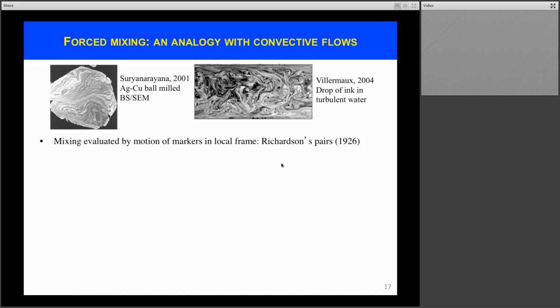What we realized is that a key point in understanding the origin of this length scale selection was to look at the mixing that's forced by plastic deformation. And here it's interesting to make an analogy with convective flows. On the left-hand side is a cross-section of a particle of copper silver that is being ball milled, but stopping before one has formed a solid solution or nanocomposite. And you see these stretched fibers or platelets of copper and silver. This is somewhat reminiscent of how materials would flow in a liquid. There's no deeper point behind this comparison, but visually this looks very similar to the transport of a drop of ink in turbulent water.